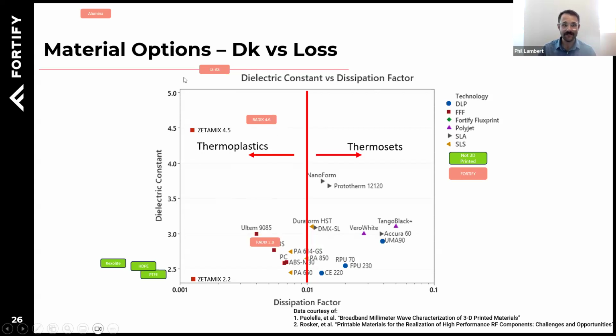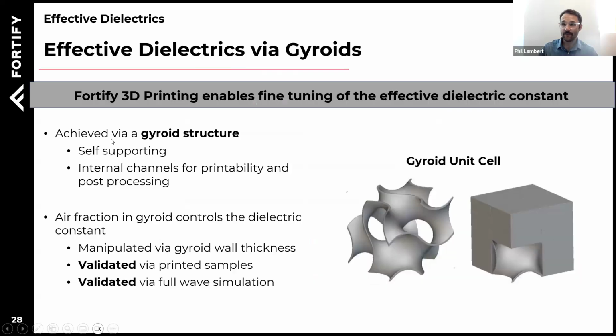And then the ceramics are generally in a league of their own as far as characteristics. Quite low loss, and definitely the alumina, can't even fit it on the chart here, sitting up at 8 dielectric constant and 0.0002 loss tangent. So very interesting materials. And we use these materials to do lensing.